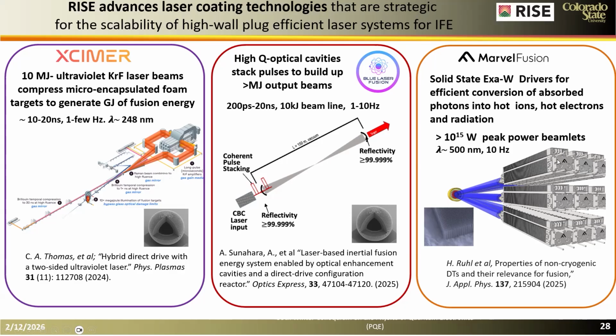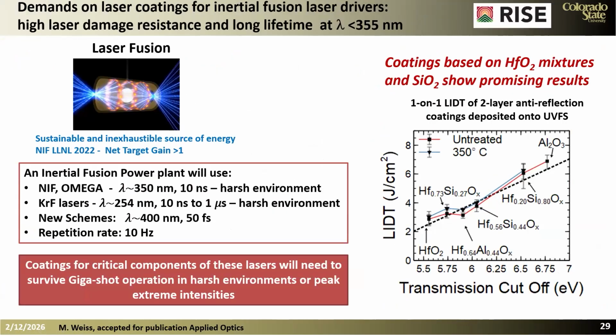essentially petawatt lasers, and there will be many of these lasers impinging on a capsule. These concepts exploit the ability to generate very efficiently hot ions, hot electrons, and radiation when these ultra high intensity pulses strike nanostructured targets. Blue Laser Fusion and Xcimer Energy will use foam targets that I show here. Now, the NIF laser operates at 355 nanometers, so we have also been doing some work on coatings for 355 nanometers.